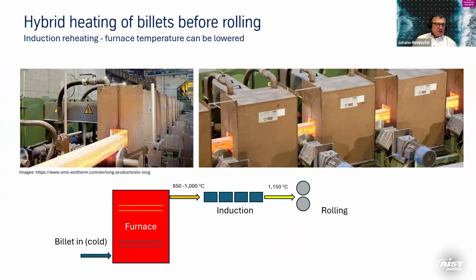And the other concept is a hybrid heating of billets concept before rolling. So you have the furnace, you come in with the cold billet, go through it, you end the furnace not at 1200 degrees, you end at 800, 900, 1000 degrees, go into induction coils and heat up to the final rolling temperature of 1150 degrees, for example. That gives you the option to minimize the exposure time at high temperatures. So you minimize scaling and you have a very, very small footprint. You can operate the furnace at lower temperature and also optimize the energy consumption of the furnaces. So that's also a good solution here shown for a square billet, 160 millimeter square.